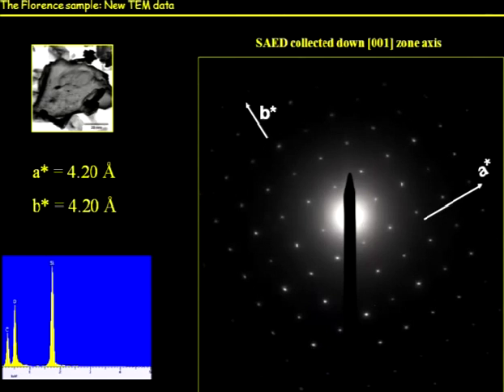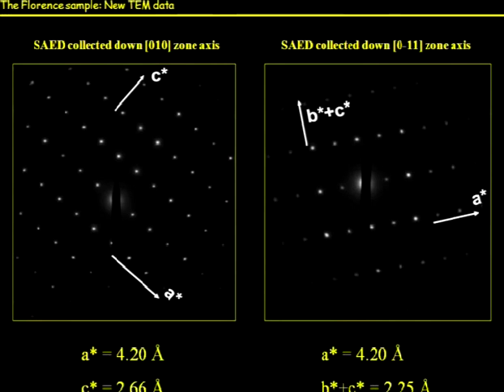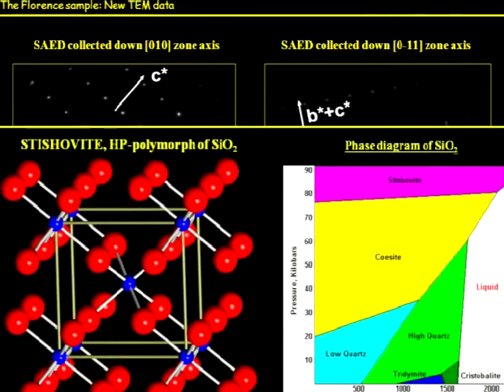In this kind of orientation, you can see something like a square. If you tilt it, you are able to obtain electron diffraction patterns for other orientations. This is the tetragonal unit cell we were able to find. The fact of having only silicon and oxygen and this tetragonal unit cell unequivocally corresponds to the mineral stishovite. Stishovite is the high-pressure polymorph of silicon dioxide. It shows this kind of structure, with silicon in octahedral coordination, so it is very high pressure.